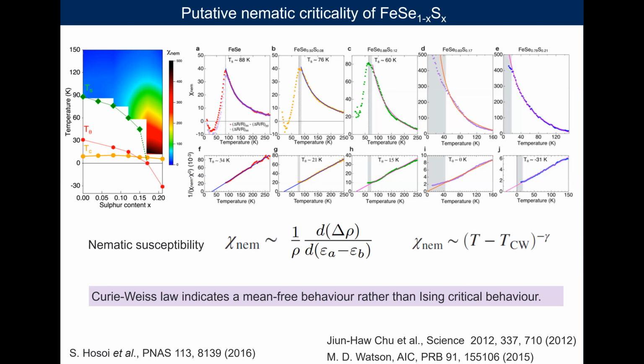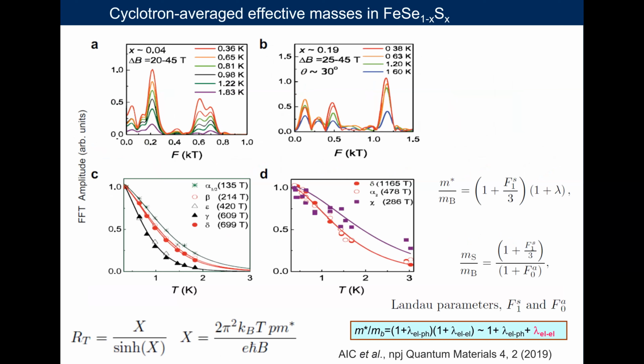Obviously, these are based on assuming a Curie-Weiss law, which normally is a mean-field type behavior. To really probe the existence of critical behavior, we need to look at the behavior of the quasiparticles at very low temperatures. To do that, one method is the quantum oscillations, and looking at the effective masses detected from these experiments. We measure the amplitude of the quantum oscillations for different temperatures. We look at how the amplitude changes with temperature, which allows us to extract the effective masses using the Lifshitz-Kosevich formulas. And these effective masses that we extract should be affected both by electron-phonon interaction and electron-electron interactions.